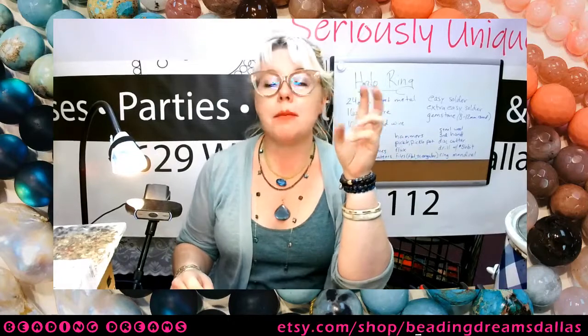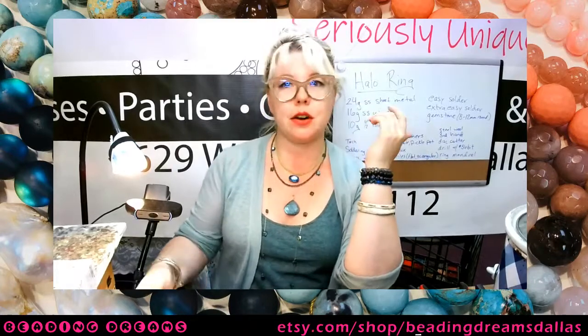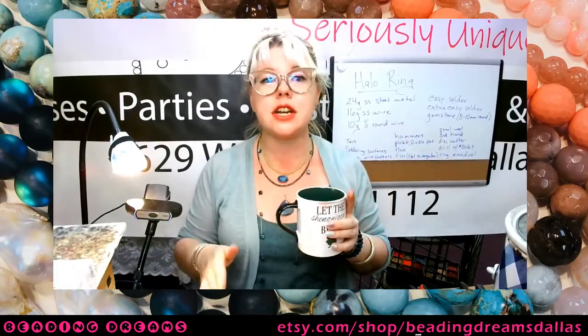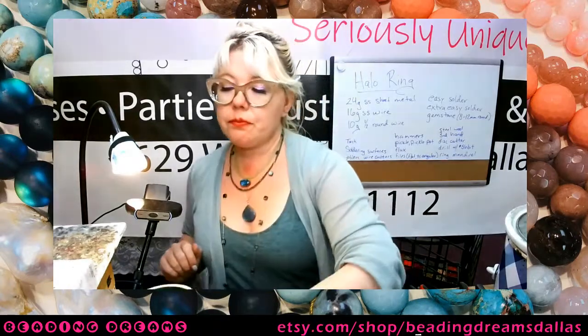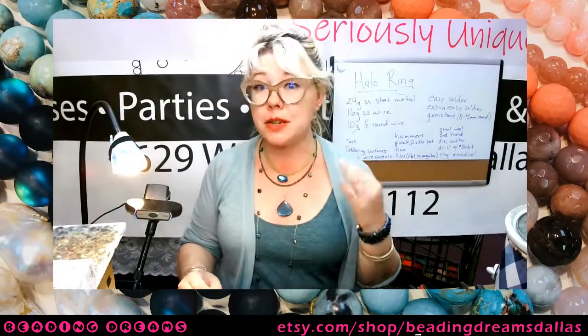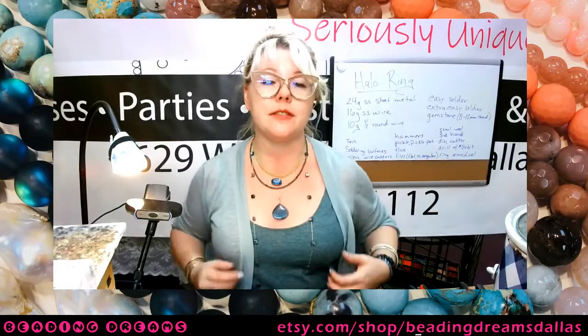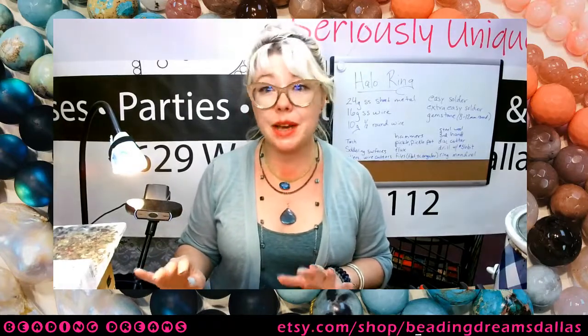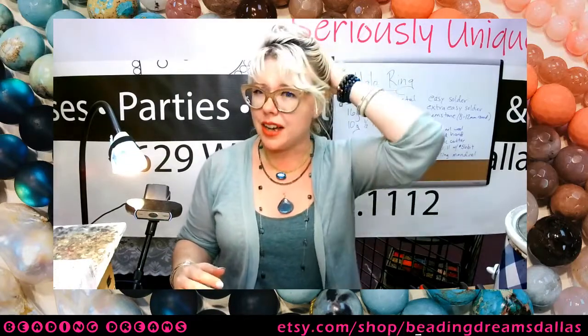10 gauge soft was a question that was just asked on the stream. Here's an interesting thing. Once you get above, I think, 16 gauge, they stop offering half hard as an option, because the wire is just so thick that having it in a half hard makes it almost impossible to work with. So once you get above 16 gauge, soft is pretty much your only option. Plus, if you're going to solder it, you will be annealing it as you solder it. So even if it is half hard, you're going to be turning it back to its dead soft state. So there's absolutely no point in ever purchasing half hard wire if you're going to solder it. But that being said, even if you have half hard wire, it'll get annealed, it'll get soft. It's all gonna come out in the wash, I think is what I'm trying to say.